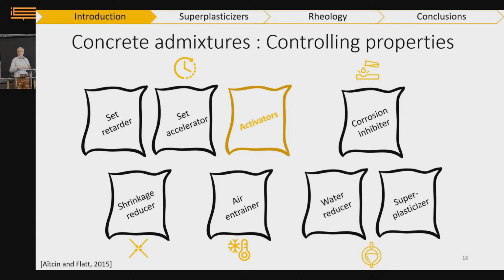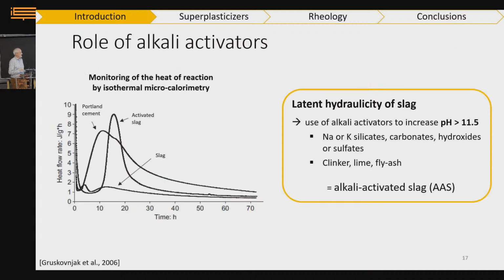Before, life was easy: we would have the calcium silicate and the calcium aluminate. We put it in water and it reacts spontaneously with water. Now we are substituting with materials that are sometimes glassy or almost always disordered, and they need to be activated. They don't react very fast with water, and we have to accelerate the reaction. This we know. This is illustrated in this heat flow rate development over time in an alkali-activated cement paste, where you compare Portland cement with just slag in water, and you see that if you put slag in water, there is no chemistry, no heat released due to any dissolution, or very little, and you have to activate to recover the reactivity that you had spontaneously in Portland cement.